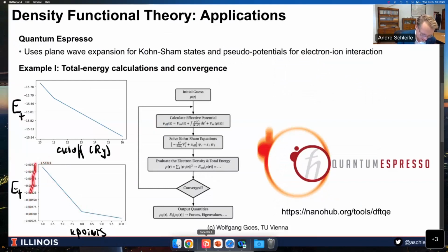So you can see actually in this case, the dependence of the total energy is much less than for the plane wave cutoff in this K-point regime that I tested here. So in this case, I just used 3 data points. You'll make a plot until this plot becomes sort of flat, or I should say flat within a level of acceptable accuracy.